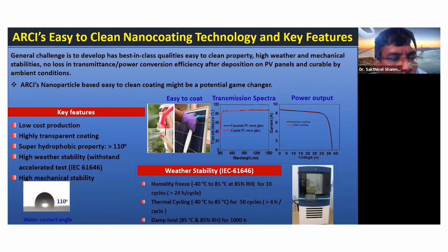So this coating should withstand the IEC standard 61646. This is a type of accelerated test which comprises a high humidity freeze test, thermal cycling test, and damp heat test. These three tests have a total duration of 1500 hours.